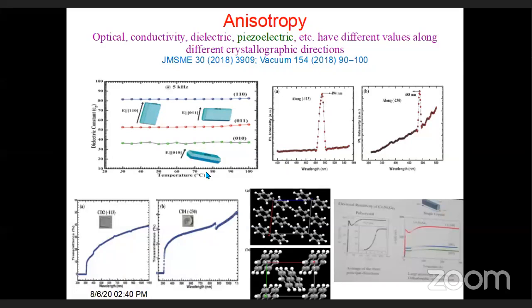So this slide is to explain a very important term called anisotropy. Anisotropy means that it is a very typical property of crystals that a physical property, for example, conductivity or resistivity or dielectric constant or even PL emission, depends on the direction. These are real experimental results of our work: if I take a crystal and measure the dielectric constant in different directions, we get different dielectric constants. Similarly, if I take the PL intensity of the same crystal in different directions, you can find the position of the PL peak is shifting.